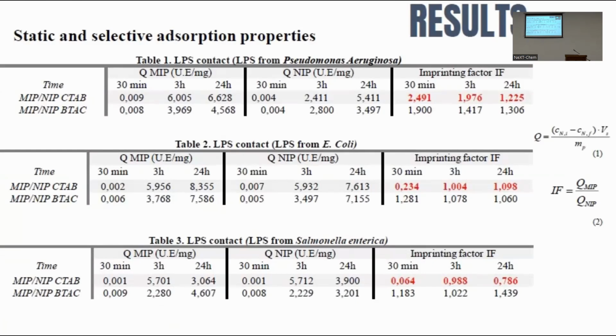To quantify the amount of the LPS absorbed after various contact times in both polymers, the absorption capacities were calculated according to equation 1, and the specificity with which MIP particles rebind LPS compared to NIPs was determined by calculating the imprinting factor using equation 2. After 30 minutes of contact with LPS from Pseudomonas aeruginosa, best absorption capacities and imprinting factors were calculated for the MIP CTAB system, leading to an imprinting factor of almost 2.5.